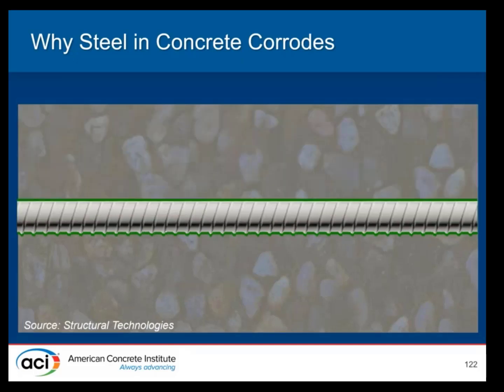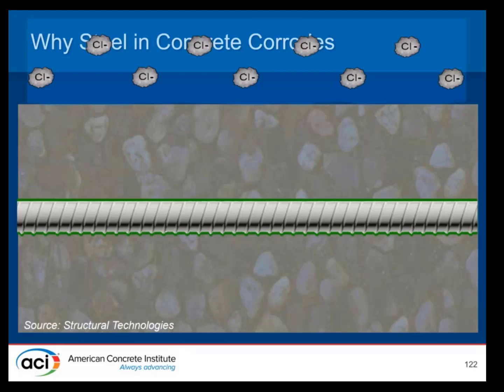So the second way that passivating layer gets damaged is by chlorides and moisture. Chlorides come from a lot of different sources. They can be salt water, de-icing salts, industrial processes, or we can have chlorides from the original concrete mix, either as an intentional admixture, which is not permitted anymore for structural concrete, but has been common in the past, or impurities in the water or the aggregates used in the concrete mix.